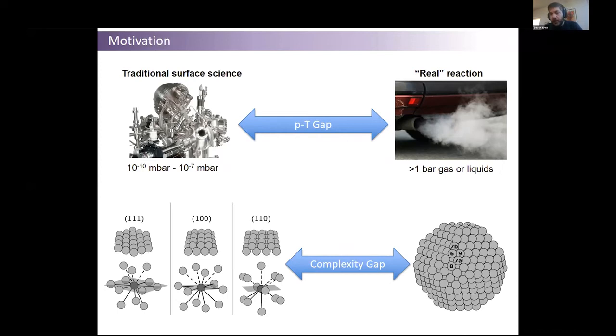The most active part of the catalysts we use today are metallic nanoparticles, but the surface science studies, and also our studies, are actually done with single crystals. Now we are simplifying our materials. Instead of using this 111 facet of this nanoparticle, we model it with a semi-infinite 111 surface. Same for the 100 facet, we model it with the semi-infinite 100 surface.